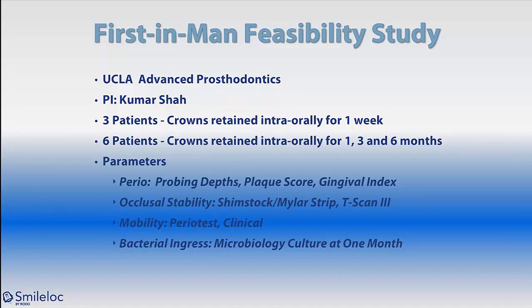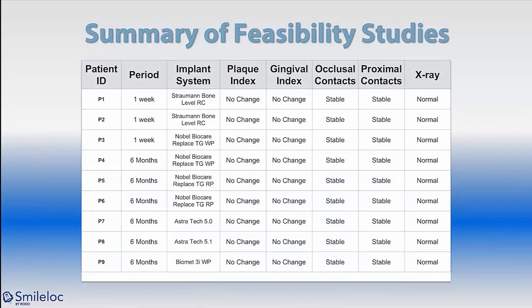Occlusal stability, they checked with shim stock, mylar strips, and T-scans. With mobility, they used the perio test and a clinical evaluation of the individual crowns. And they did a bacterial ingress test with microbiology cultures at 1 month to see if there was any bacterial contamination. They were done on Straumann, Nobel, Astra, and Biomet implants.